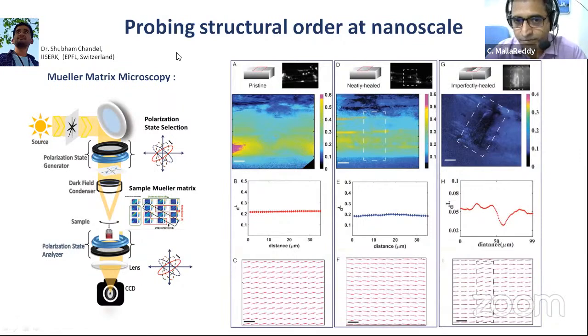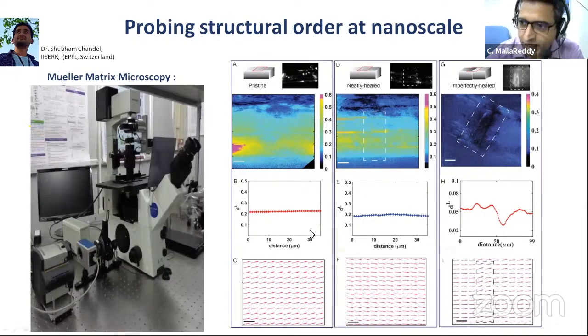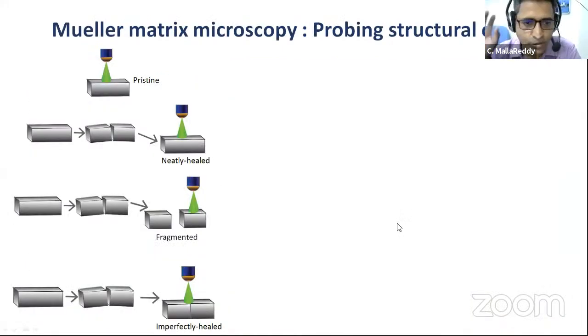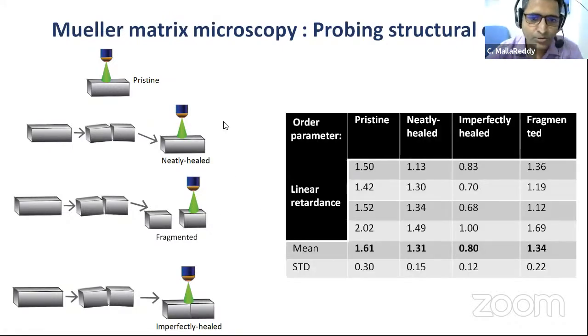This tells that this is a very good technique, and we can go to at least micrometer, if not nanometer scale, and we could see these changes in the parameters. I'm not going into the details here, but this technique could give us a quantitative estimation of the self-healing. So this tells that in our case, whenever there is good self-healing, it is really good for crystallography purposes. You don't see much difference in the neatly self-healed crystals. So these are the parameters.